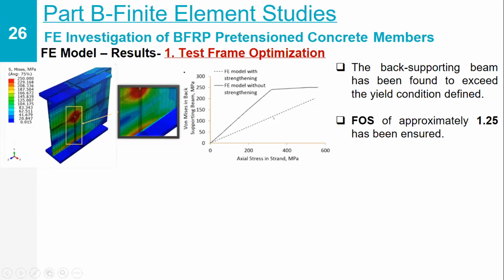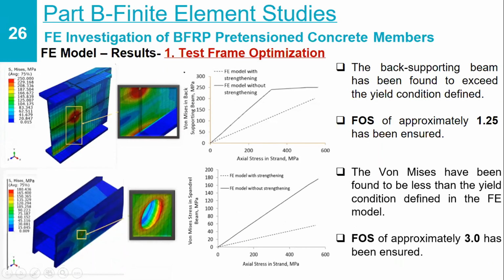And we can see the reduction in the stresses that generate after the addition of the stiffeners, or the strengthening. Also, the spandrel beam has been modeled, and additional stiffeners have been provided based on the result to get a higher factor of safety, because this beam will be directly subjected to the load during the pre-stressing applications. Hence, a higher factor of safety has been achieved by providing additional stiffeners, even though it was observed that the stresses in this beam did not reach yielding due to the application of the pre-stress.